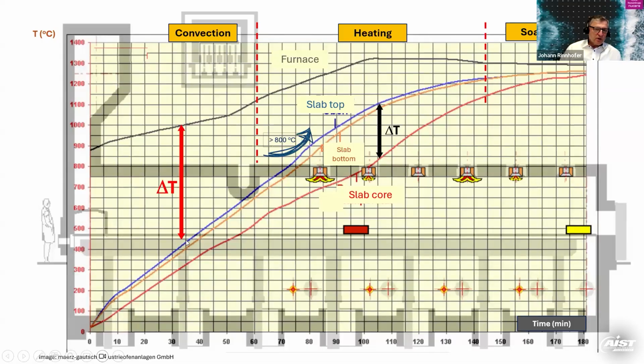So what we always have to look at is the temperature difference in the slab. This is shown here as the delta T. It should not be too high, because we can get all sorts of mechanical problems in the slab, including cracks, when this temperature difference is too high. So we have to watch the temperature difference in the slab. We have to watch the surface temperature of the slab, and in the end, we want to come out with a very equal temperature, say plus minus 20 degrees or so, in the slab. That's usually good enough for rolling a slab of 200 mm thickness. So this is why we have the soaking zone on the end.